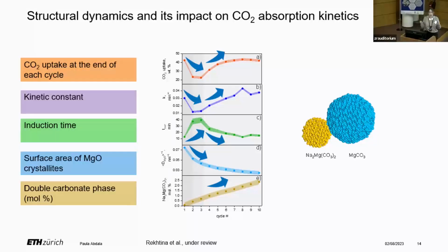Now, what could be leading to the deactivation? Well, we thought if we need the magnesium oxide surface to nucleate the magnesium carbonate, a decrease in the surface area of magnesium oxide could be one reason. If we plot the surface of the magnesium oxide crystallite, so 1/d, we see a decrease, especially already at the initial cycles. Cycles 2 and 3 have the biggest drop, but it continues to decrease. So this is not the only parameter.